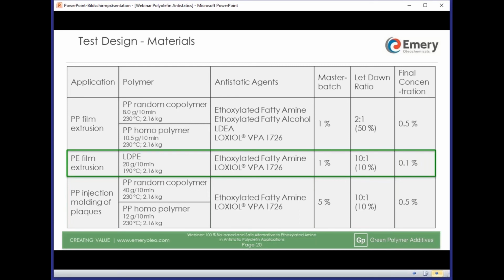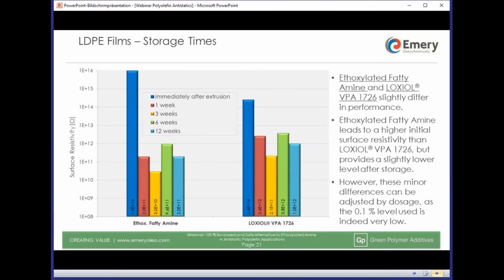In PE, we continue with 2 result slides in PE films: antistatic performance depending on time and on humidity. Storage time. You see we have fewer columns as we check just 2 antistatic agents instead of 4. And you see the antistatic performance is overall similar. Comparing the dark blue columns, ethoxylated fatty amine shows a higher resistivity value right after extrusion, then coming down to a little lower level than LOXIOL VPA 1726. Remember, we used a very low dosage of antistatic agent here, just 0.1%. You for sure can go higher than this to adjust the effect further if needed. So we are not seeing any crucial difference.